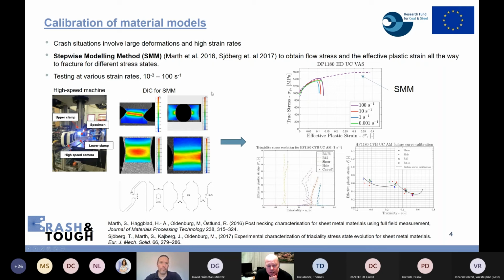And this method is based on the use of digital image correlation. So you can see here some 4 examples. And what you can also see is that we're using different kinds of geometries of these specimens. You have a shear, you have a hole in order to have this plane stress, you have a notch to get the very important plane strain condition that Pascal mentioned in the previous presentation. So as an output, besides having the flow stress curve, you also get the triaxiality history from where plastic deformation starts to the final fracture for all different specimen geometries, which is correlated to different triaxialities. And this is, of course, used to calibrate the failure model. In this case, it is the modified Mohr-Coulomb.